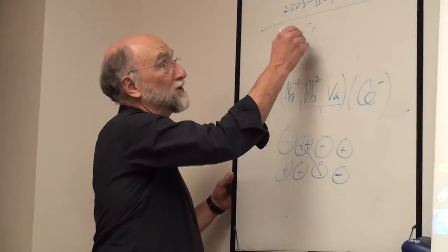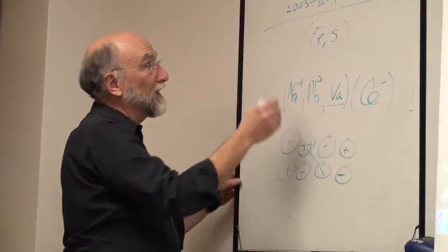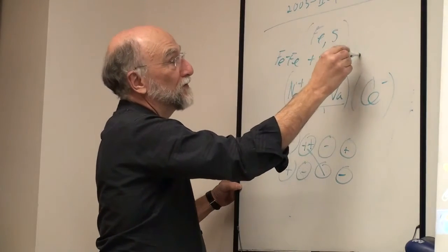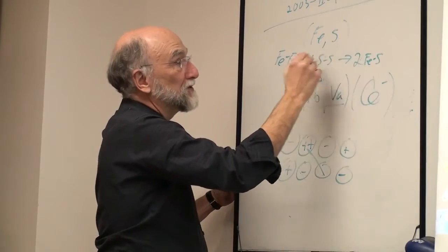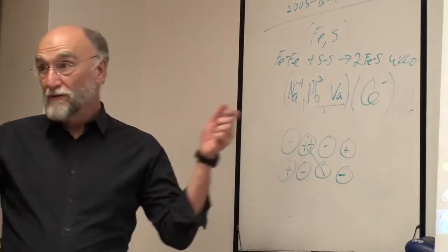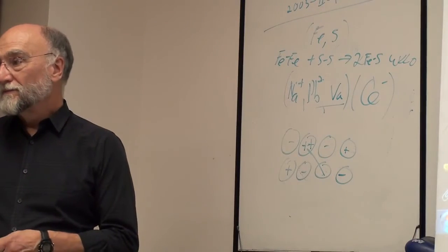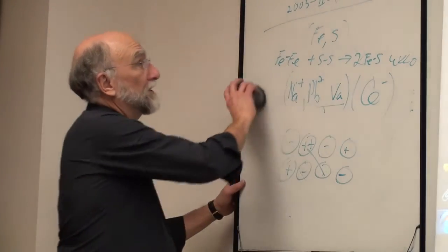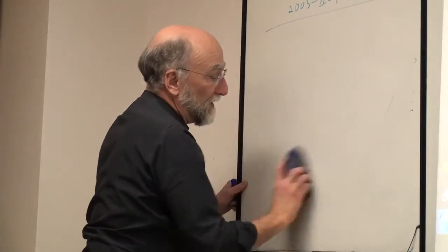So everything's just on one sublattice, iron and sulfur on the same sublattice, but your iron-iron pairs plus your sulfur-sulfur pairs form FeS pairs. The omega would be very negative for that, so the iron and sulfur tend to form pairs because iron and sulfur have very different electronegativities. One's a metal, one's a nonmetal.